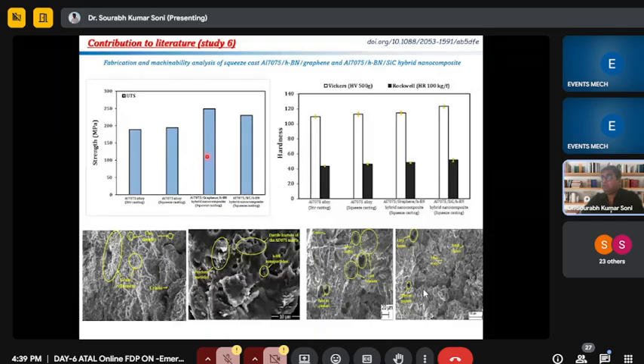Here I observed the strength of the aluminium 7075 and hybrid composite specimens. I observed that the graphene HBN hybrid nanocomposite has better mechanical properties compared to the others. But in the SiC composite, SiC HBN, I have observed more hardness because the SiC particle is a ceramic particle, and ceramic particles are mostly used to improve hardness and wear properties. So we can cite the literature also, and we can claim our result also.